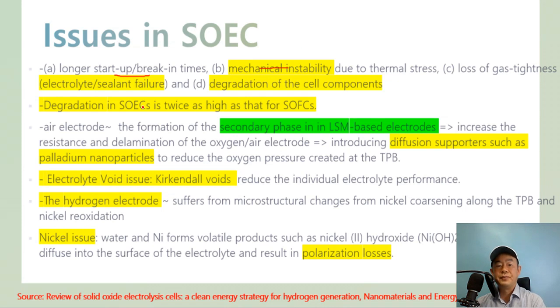For the air electrode, the formation of a secondary phase in the LSM-based electrode is a problem. For the electrolyte, there is a void issue called Kirkendall void, which reduces the electrolyte performance. The Kirkendall void is the void at the interface between two metals that occurs as a consequence of a difference in the diffusion rate of materials. The hydrogen electrode suffers from microstructure change from nickel coarsening along the TPB and nickel reoxidation.